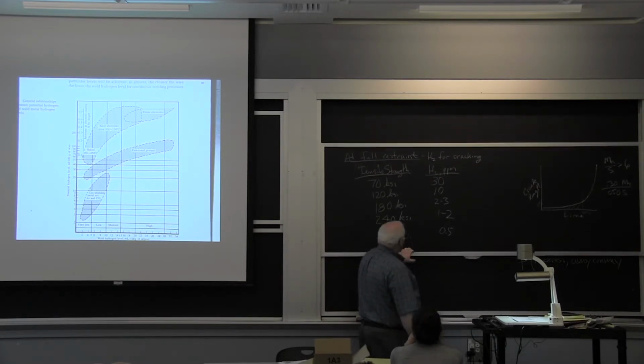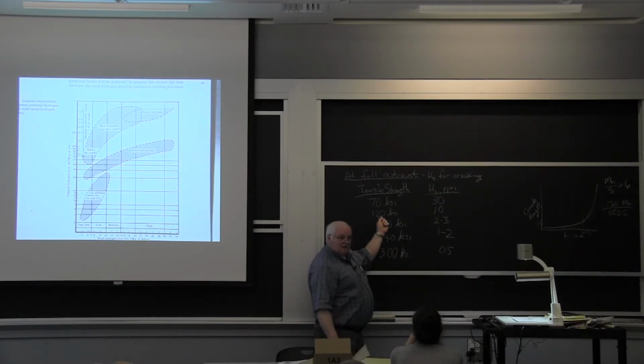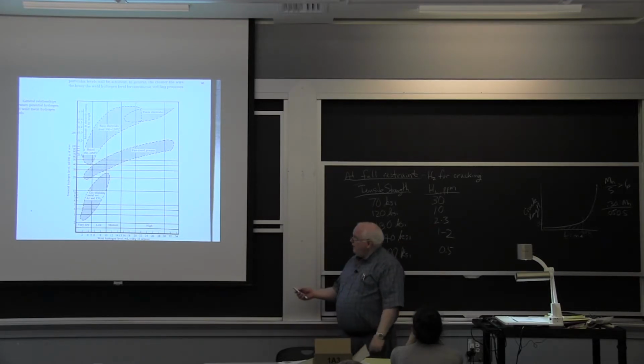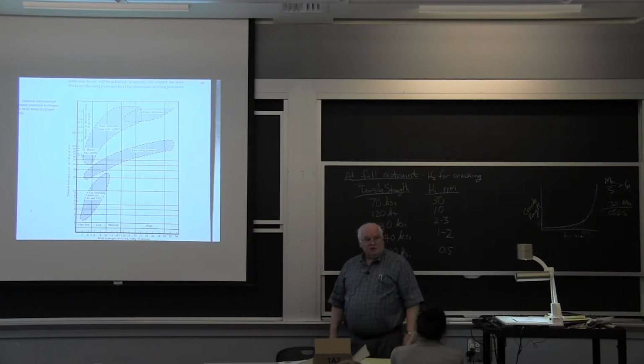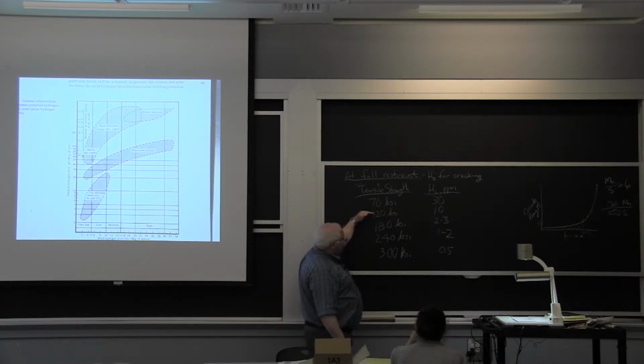What happened with the Seawolf, they had weld metal that was on the high side chemistry, had enough hardenability. They were at about 150 KSI yield, which would be more like 180 KSI tensile, 2 to 3 parts per million hydrogen, and guess what? You have a hard time achieving that even with the best control in the shipyard. That's why they got hydrogen cracking. They thought they were welding HY 100 and they should have been around here like 130 tensile, but in fact the weld metal was 180 tensile because it had lots of extra alloying. It was on the high side of the chemistry.